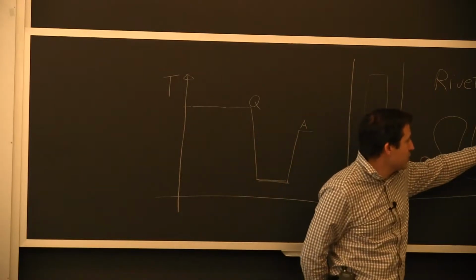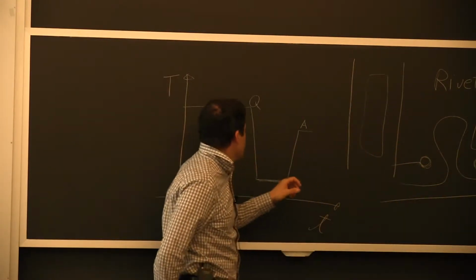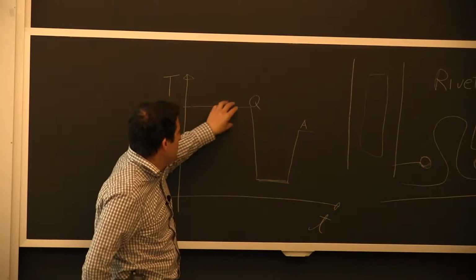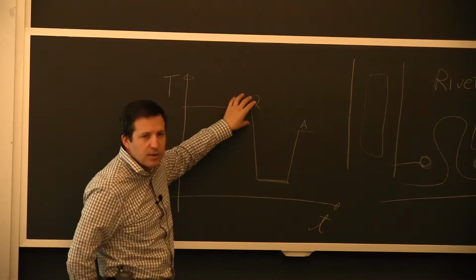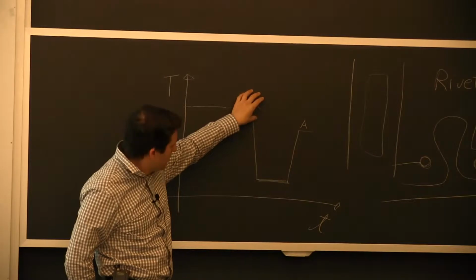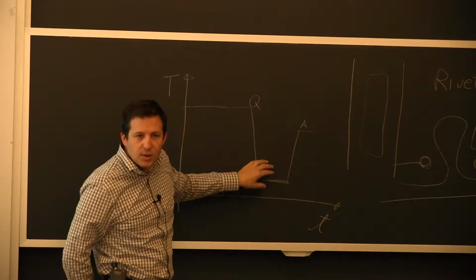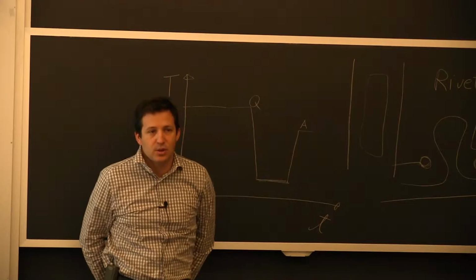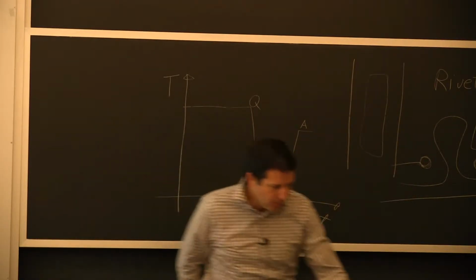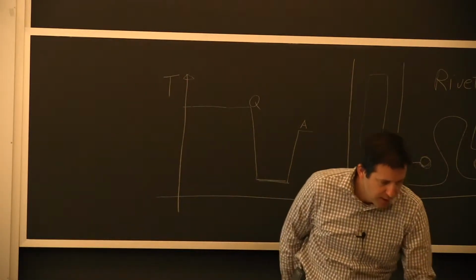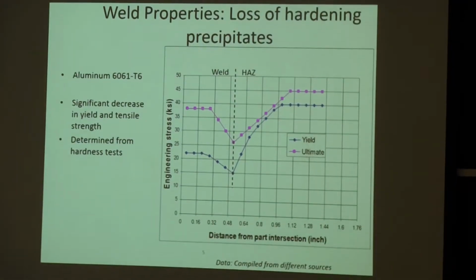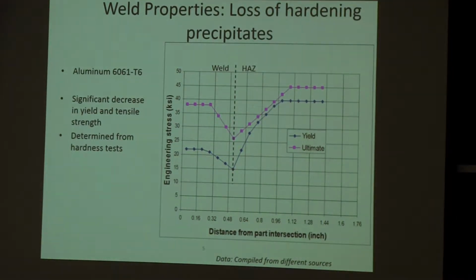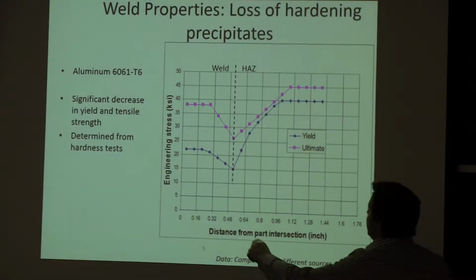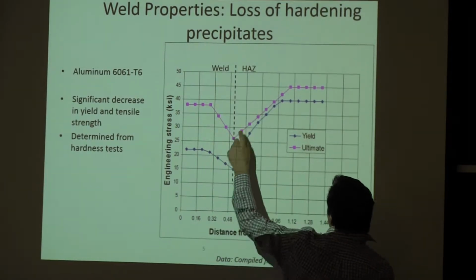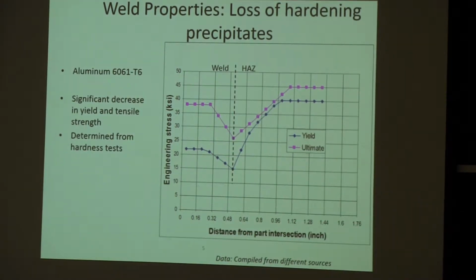If you have this material and you weld it, you fuse some area, and there's another region next to the fusion, the heat affected zone, that gets heated up and cools down really fast. So you will lose your precipitate in that zone. I'm actually showing this right here. This is to illustrate, Professor Eagar mentioned a factor of 2 reduction in strength. So that is here, this pinkish curve. But for yield strength, it's even more.